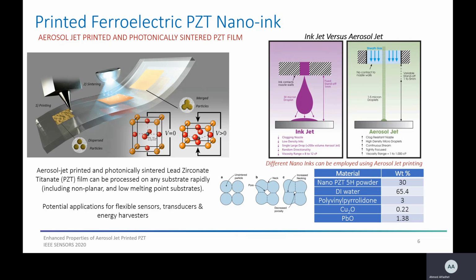So the PZT nano-ink was prepared from particle-based powder and a solution medium, and by reducing the particle size and adding sintering aids, we lower the sintering temperature. We have a larger surface area that results in higher surface energy, the high surface area of the smaller particles resulting in higher surface energy, which is the main driving force in the sintering process.